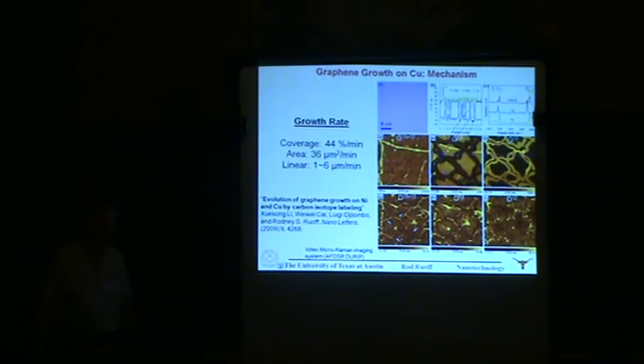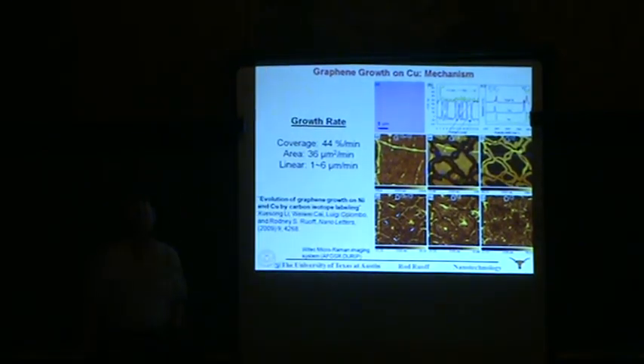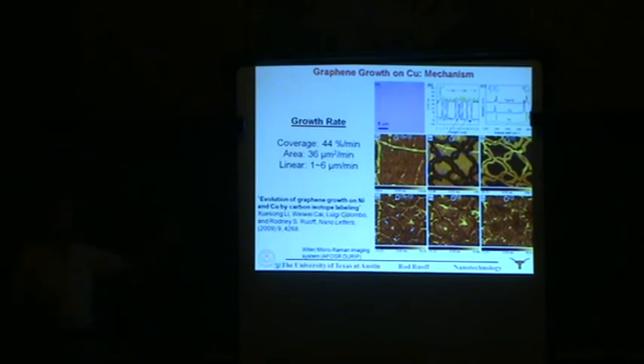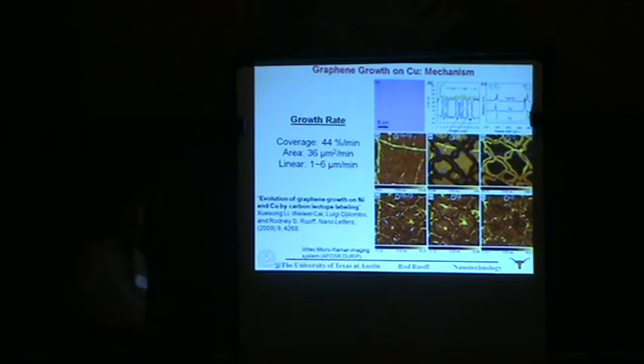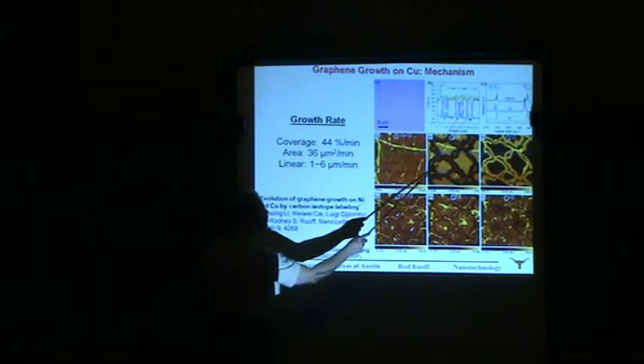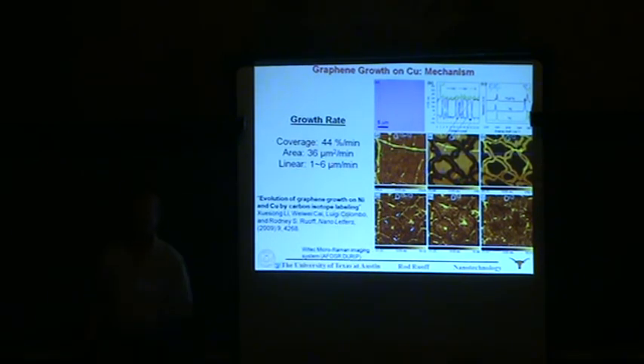We can then use micro-Raman mapping microscopy, and it turns out that pure C13 graphene has a G-band in the Raman spectra which is shifted dramatically from normal graphene by 60 wave numbers. So then it's trivial with this sort of instrument to assign a spectral bandwidth that is only collecting, for example, the peak at 1520 and not the peak at 1580 that's given by normal graphene. And by doing that, we get a color-coded map in which this region here, for example, is C13 graphene. This is normal graphene, or essentially C12. This region here is C13, and growth was terminated after the third minute.